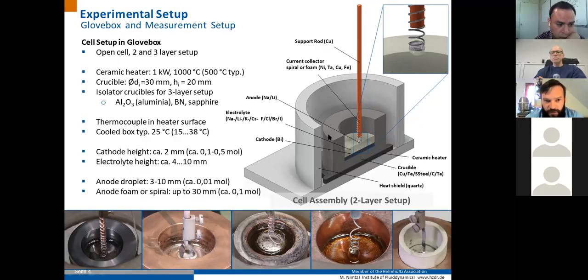This is shielded by the quartz shield, and this also leads to a high temperature gradient from the bottom of the crucible to the top, and also inside the cell itself there are temperature gradients, so there's always some convection possible due to different temperatures inside the cell. Cathode layer heights are about 2 millimeters roughly. The electrolyte lowest possible usable height is about 4 millimeters. Most experiments use electrolyte layers of up to 10 millimeters. This is to avoid short circuits and to provide a good contact surface between the electrode and the electrolyte.